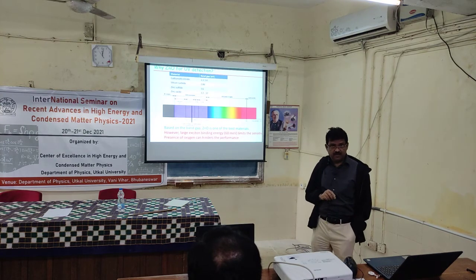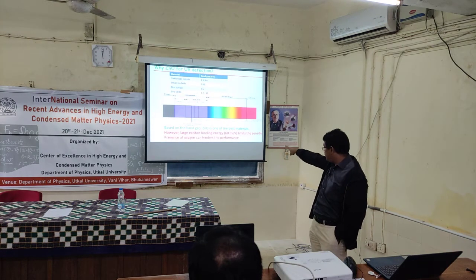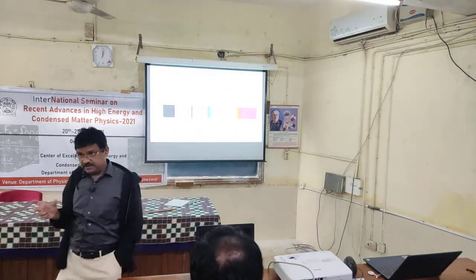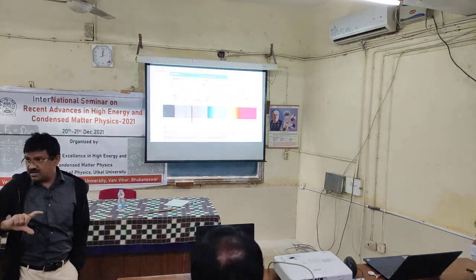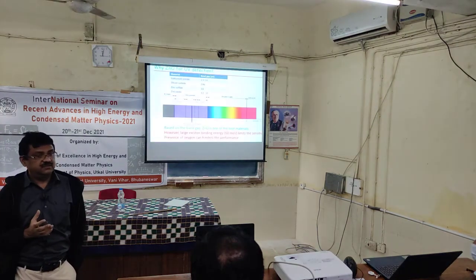But the problem associated with it is the exciton binding energy. The exciton binding energy of zinc oxide is 60 meV, whereas that of gallium nitride is around 25 meV. And what is the room temperature? 300 K. If you convert 300 K into meV, it comes to around 26 meV.